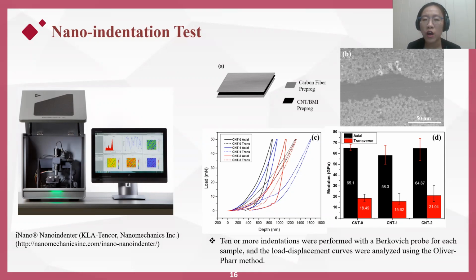are more sensitive to the load transfer between CNT and the resin matrix, compared to the compressive properties reflected in the nano-indentation test. The modulus improvement could also be attributed to the fact that the nanoscale nano-indentation test excludes the influence of discontinuous CNT bundles. Interestingly, the anisotropic ratio from the nano-indentation test of the CNT composites was also around 3, which is very similar to what we have observed from the tensile and electrical conductivity measurements.